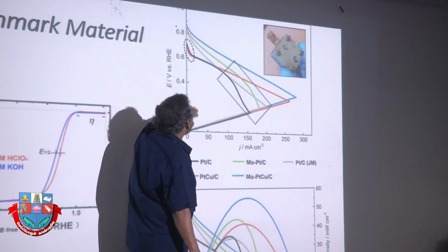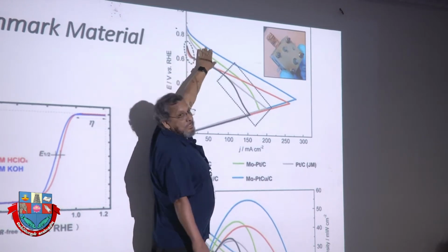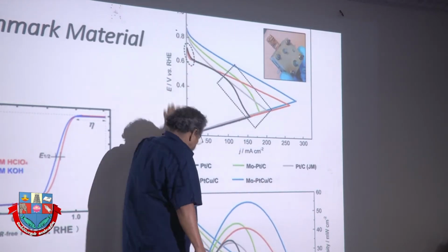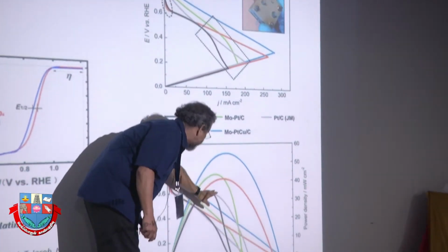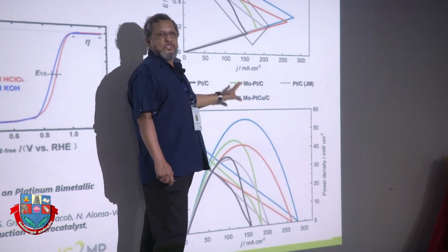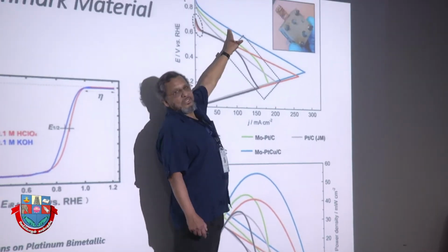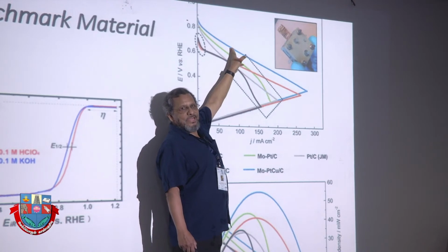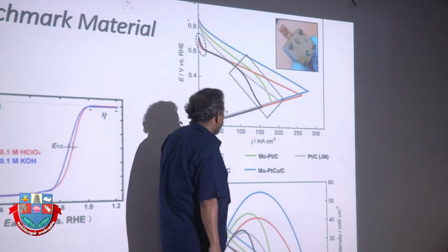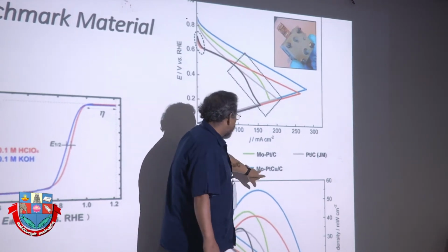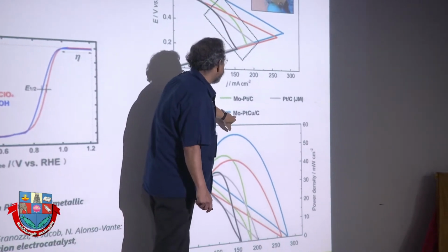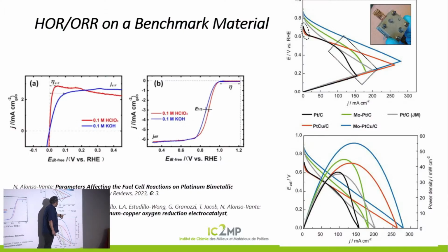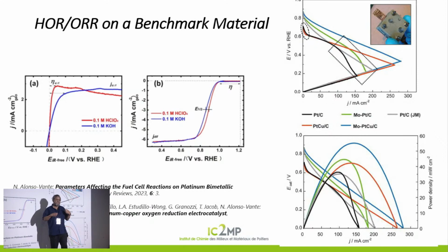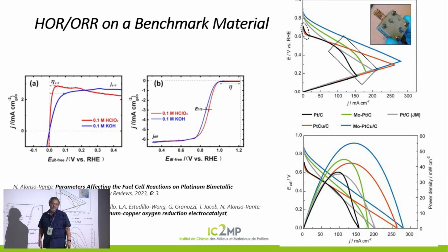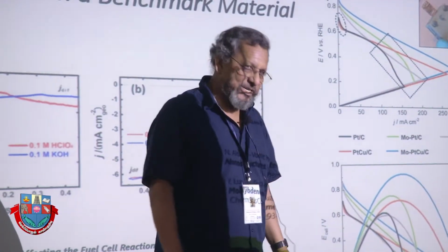Okay, so we see here that the improvement of the cathode is really very important, because the power density is increased by 60% just by modifying in an intelligent way the catalytic site of platinum. In that case, it was done using a small amount of molybdenum and making a small alloy with copper. As you see, the system becomes more and more complex. You want to have a better system to make reactions.